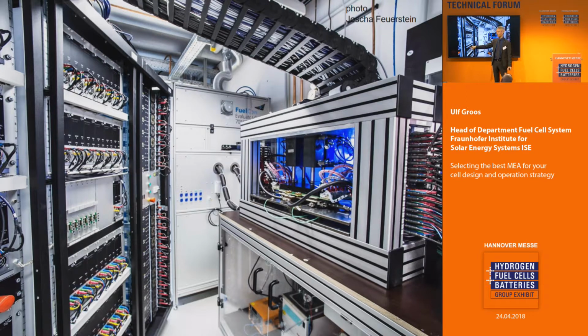So in this case, we would use 25 potentiostats together with 25 frequency response analyzers. Then we can do impedance spectroscopy on a segment level. So we see the development of the current, of the power, and of course the impedance, and how it behaves along the channel from inlet to outlet in each segment.